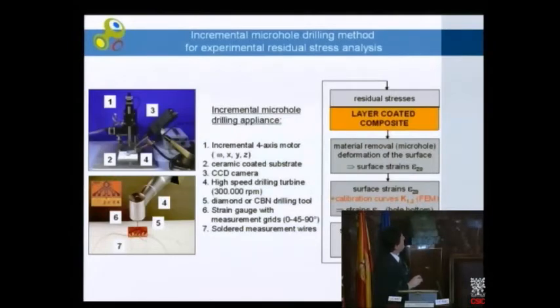So the analytical tool is shown here. That is the so-called microturbine. We measure the surface stresses, and these surface stresses are transferred to the strains in the depths at the bottom of the hole we create by this micro machining operation, and we calculate the stress depth profile by the stepwise drilling and milling operation. So typically 5 micron stepwise from the surface to the bottom, and this allows us, depending a little bit on the material, to analyze the stress distributions up to a depth of 1 millimeter.